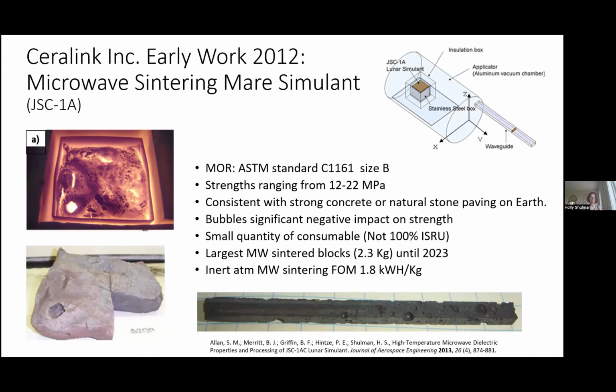And if you see on that bottom left, there's a pretty good sized block, something like almost 2.5 kilograms. And I use a figure of merit in kilowatt hours per kilogram to help get an understanding of the energy usage, because I'm always focused on energy efficiency. And so in an atmosphere, argon, it's going to take more energy than in a vacuum, because we're also heating that atmosphere.